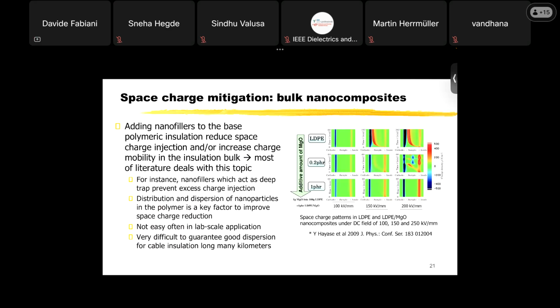I show you a few examples of these nanomaterials that can be used to reduce space charge. For instance, we can add nanofillers to the base polymeric insulation and try to reduce space charge injection or increase the mobility of charge in the insulation bulk. Because if you remember, in this way, we can avoid having heterocharge accumulation. The example that you can see here, that is used for some Japanese cable for HVDC, is using magnesium oxide.